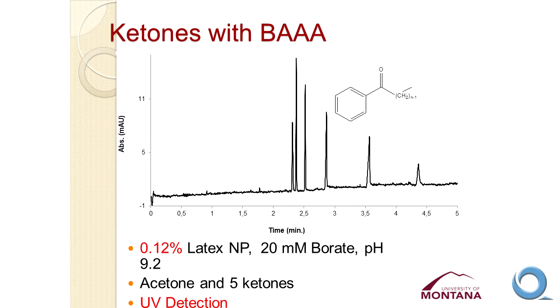We do see some odd shaped peaks in the center of the separation that we still don't really understand what's causing. And we're able to use UV detection. In spite of the fact that these are nanoparticles and they scatter light, we can still use UV detection and not have to worry too much about the interference from the nanoparticles.